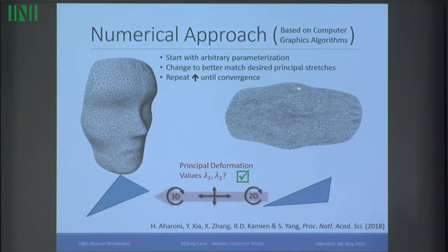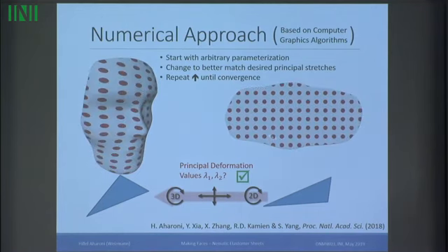This means that the deformation that takes this coordinate patch onto this surface deforms each and every triangle by factors of lambda 1 and lambda 2 along some direction. Namely, if I now tile the plane again with tiny circles, they all become identical ellipses on the surface with principal values lambda 1 and lambda 2. So this gives me an approximate global solution.